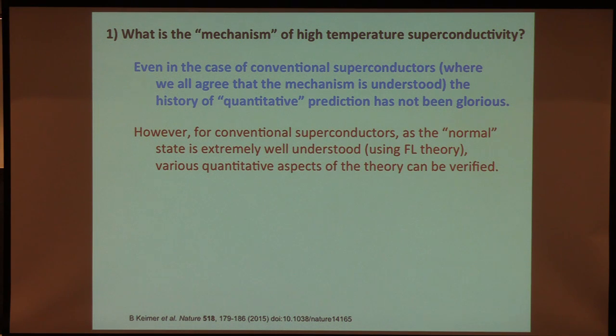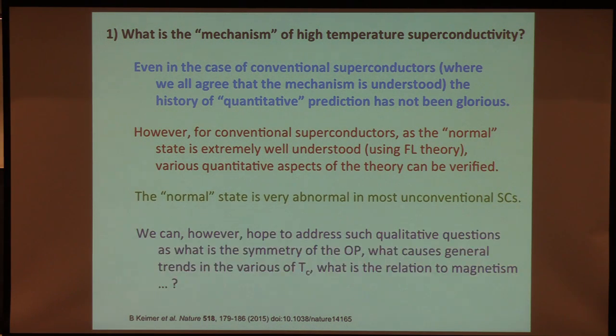And because there are other things we can test, there are some quantitative predictions that can be made based on the theory. Most of those are predictions of mean field theory. And that's where we're going to be in worse shape here, because at least in conventional superconductors, the normal state is understood with great precision because it's a well-developed Fermi liquid with sharply defined quasiparticles. And as I mentioned in the beginning, that's not the case in the high-temperature superconductors. So I propose that the statement "we understand the mechanism of high-temperature superconductivity" should be accepted at a lower standard of proof than it was for conventional superconductors. That's what I just said.